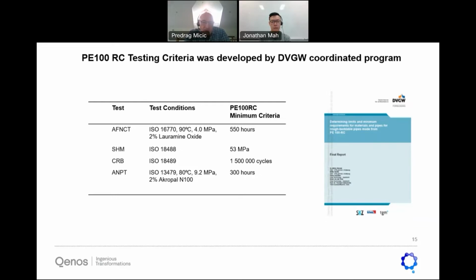And this test specification now allows us to have QC, QA methodologies to make the product and test it, but also in the field. But it will also enable fast development times, because as you can see here, they are not really too lengthy. The lengthiest one is 550 hours, which is about a month, which is a significant improvement over 1 year plus, which was previously there, including in our POP 16, including in PAS 1075. There were criteria there before. Now we do have a much more practical approach to how to test these materials. They're very complex tests.